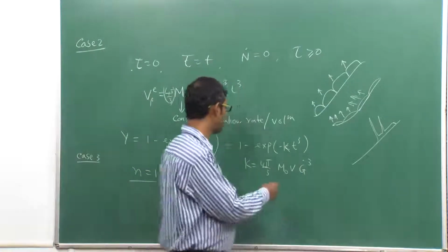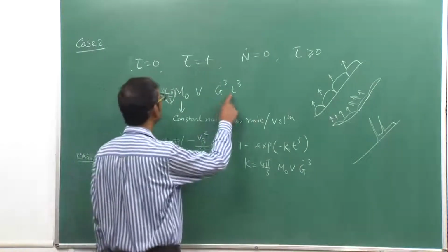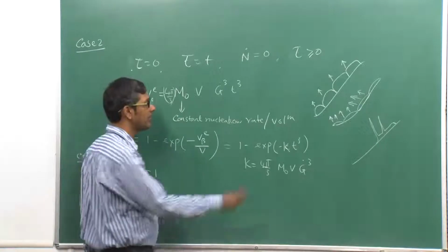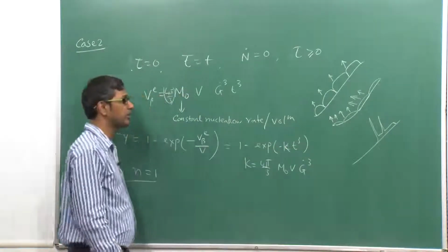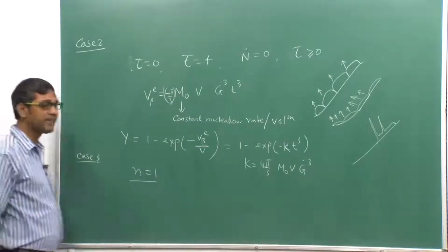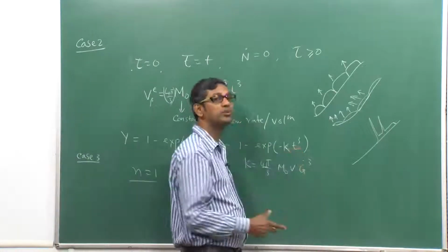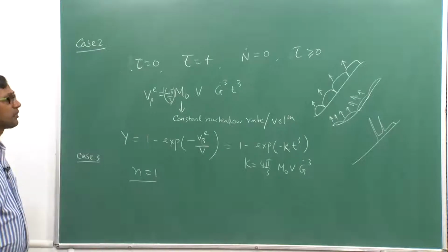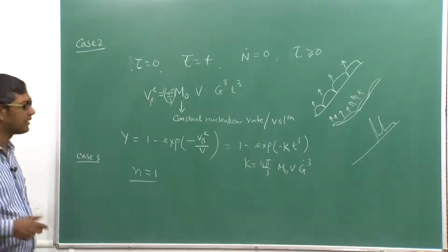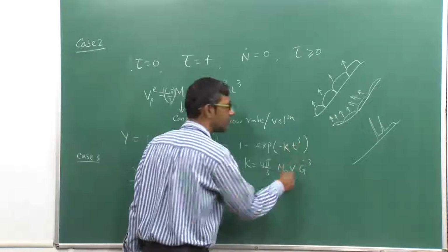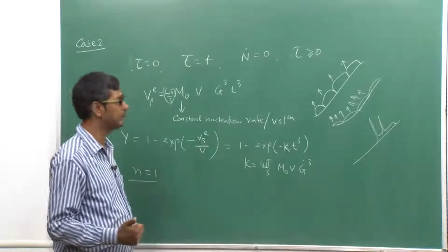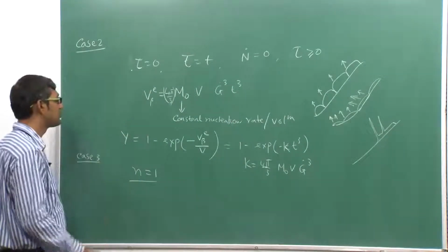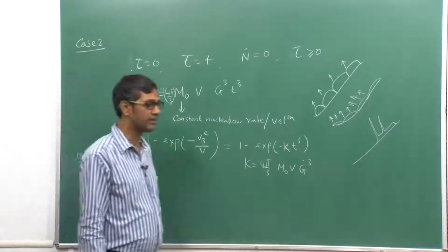So you have seen when you have 3 dimensional growth, on the pre-existing nuclei, the exponent of time becomes 3. So that means this exponent of time is basically telling you what are the different modes of the growth. If the modes of the growth are actually multiple, then this becomes more than 1. If it becomes singular, then it becomes 1. So that is the difference you should know very well in the literature.